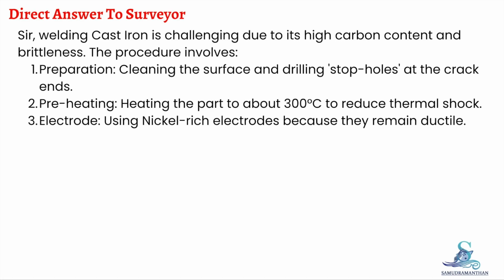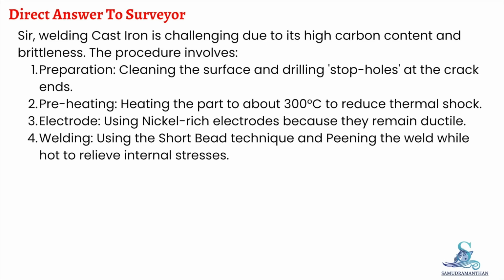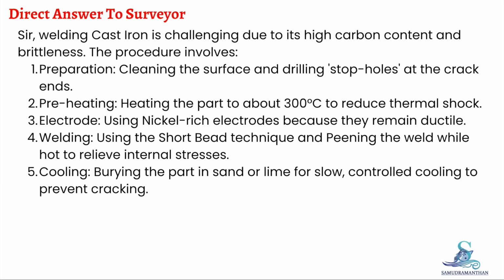Electrode, using nickel-rich electrodes because they remain ductile. Welding, using the short bead technique and peening the weld while hot to relieve internal stresses. Cooling, burying the part in sand or lime for slow, controlled cooling to prevent cracking.